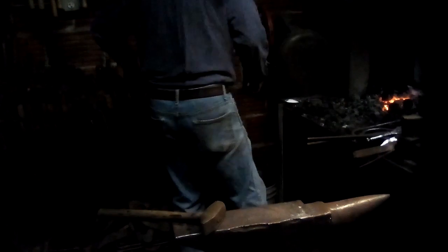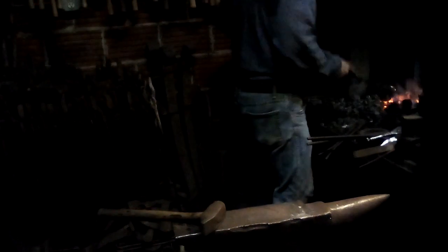Now I've got to put it in the fire on its back, so to speak. I put it edge up in the fire, and I have to get it above the critical temperature to take the stress out of the little piece of carbon steel that is in there, because it would be bad. So all I'm going to do is get it up to a dull red, and then I have some fly ash, which I use as my annealing media, and I'll just put that in there till tomorrow.